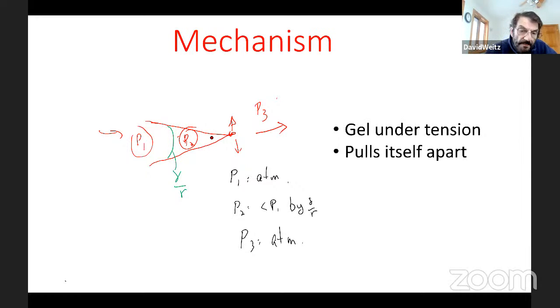And so when you put a lower pressure here, it actually tears itself apart because it's being held to the walls and it's trying to pull itself apart. And that's exactly what you see. So you're seeing essentially a tearing mechanism of this particular sample because of that. And it's being driven by this low pressure that you're inducing because of the Laplace pressure. And that's why you always have this water layer here that's actually driving the crack, and you always see it.